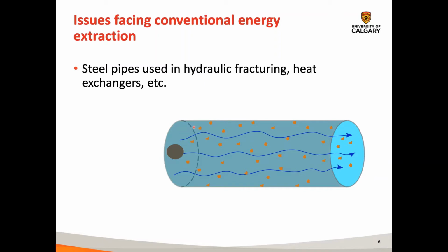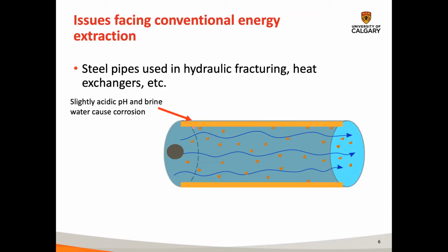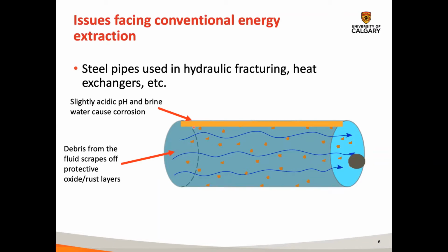Also, where the heat exchangers are flowing water that contains some kind of debris and it's salty. So what happens is the slightly acidic pH of the water and the salt in the water causes corrosion. So you get rust formation or scale formation on the inside of your steel pipelines. And then the debris from the shale that you've fracked or that you pumped through comes off, and it hits this rust and basically removes it. It scrapes it off, and then you reform a protective oxide layer on the bare steel.